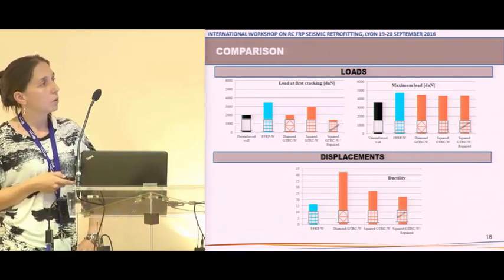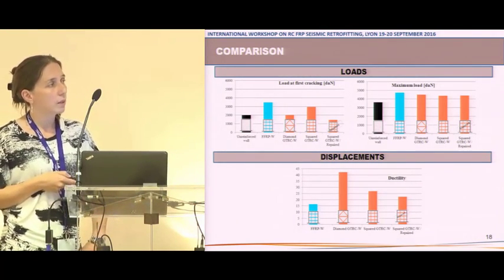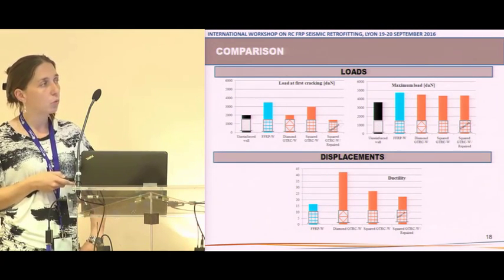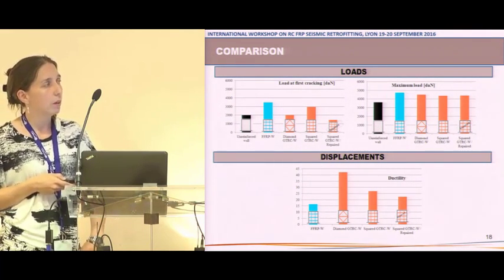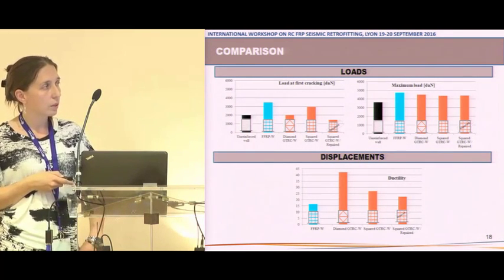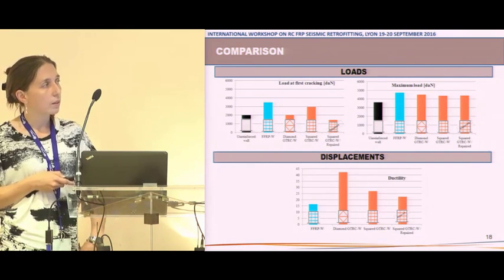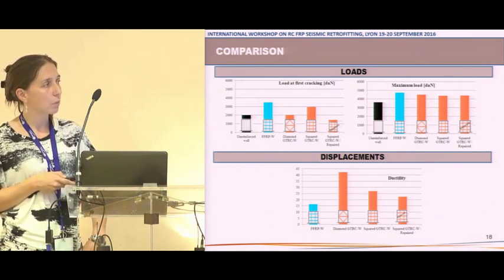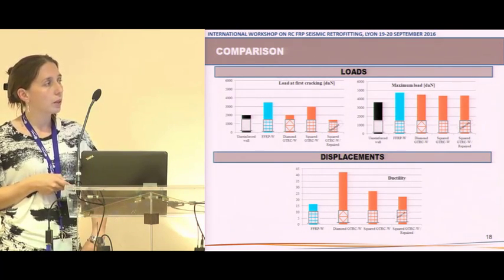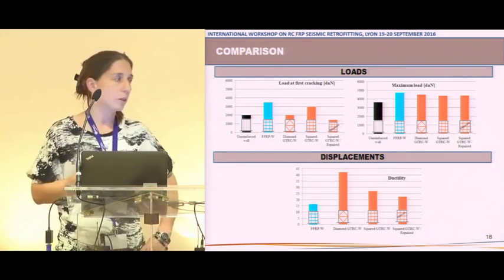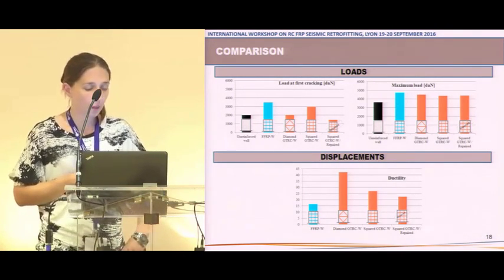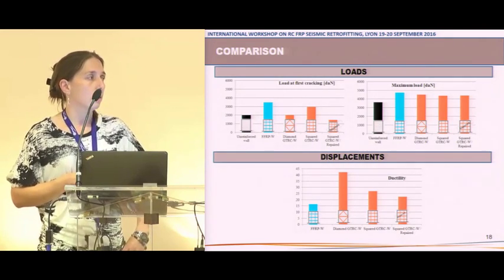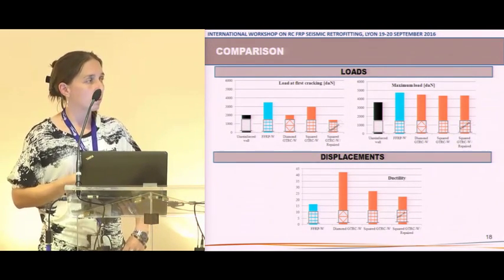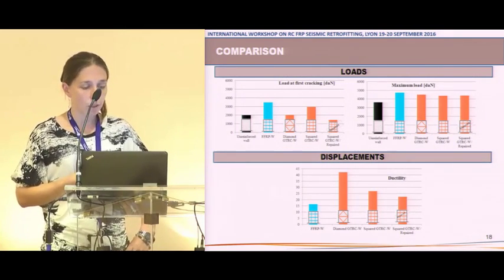If we compare in terms of loads and displacements, all the repaired and reinforced walls have about the same maximum load, but it is interesting to note that FRP is able to delay the first macroscopic damage. If we look at the displacements and compare the walls with the ductility coefficient, we can see that TRC enables a greater increase in this coefficient than FRP.